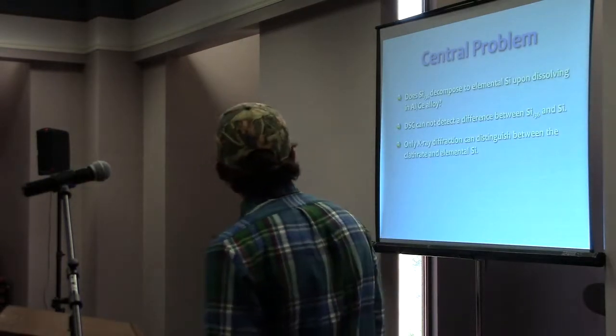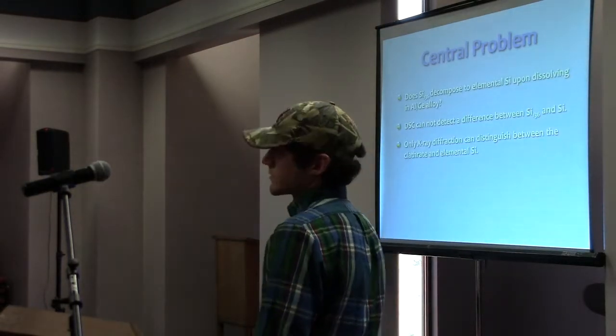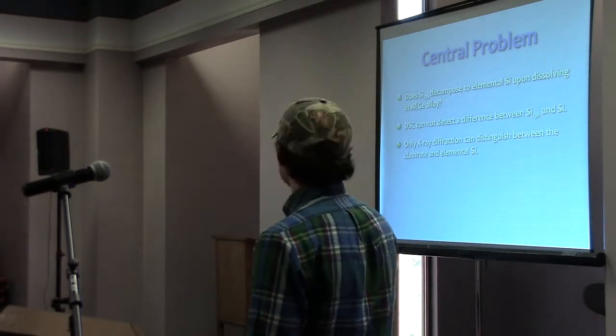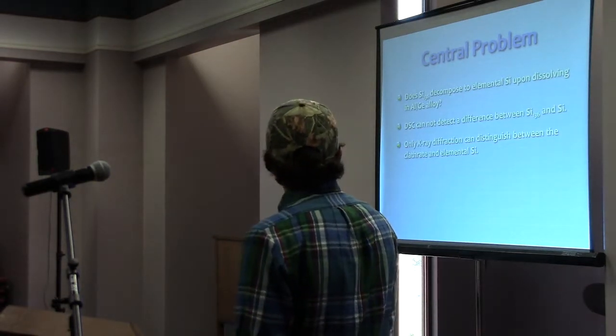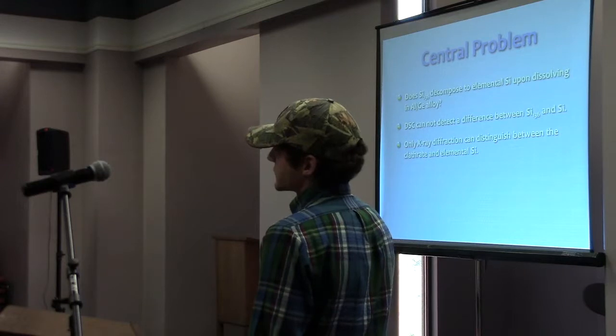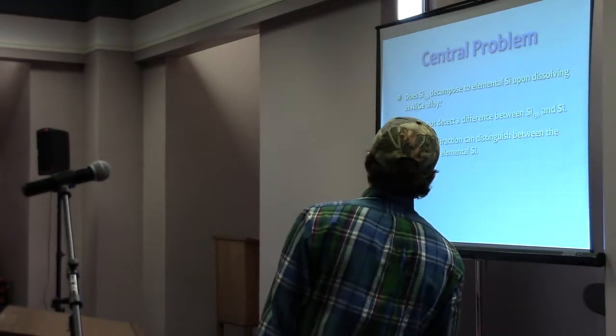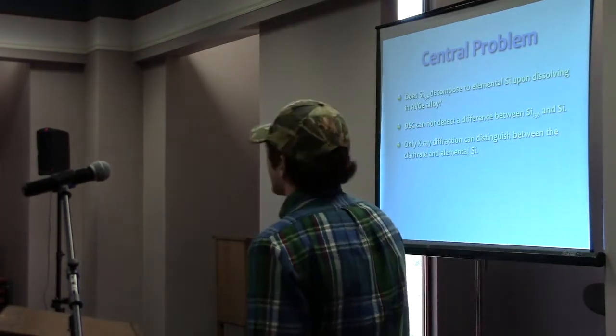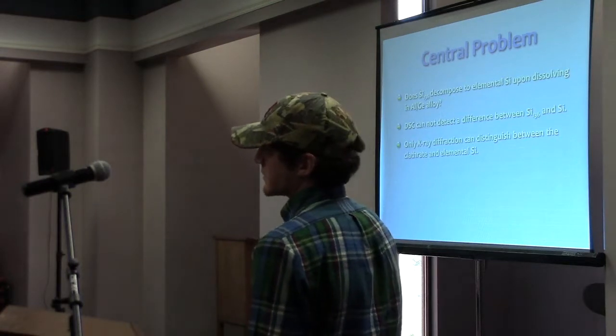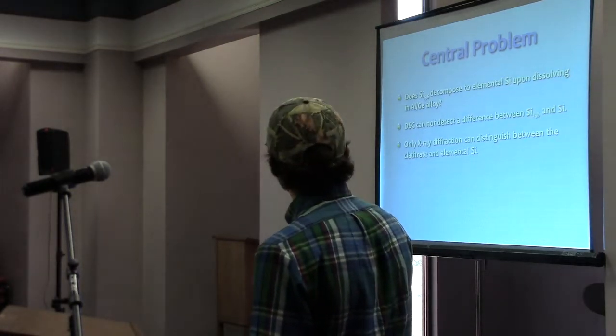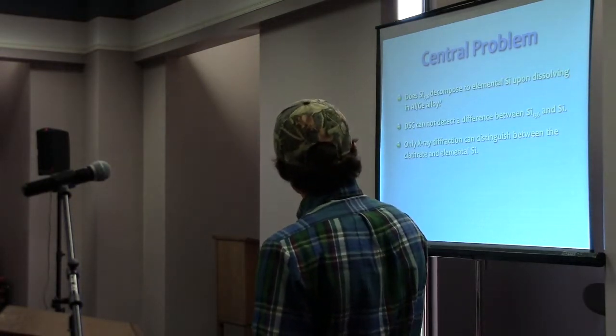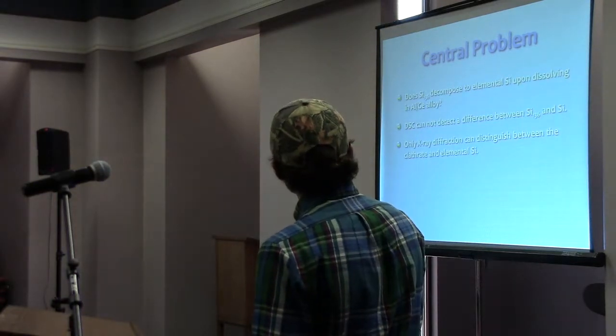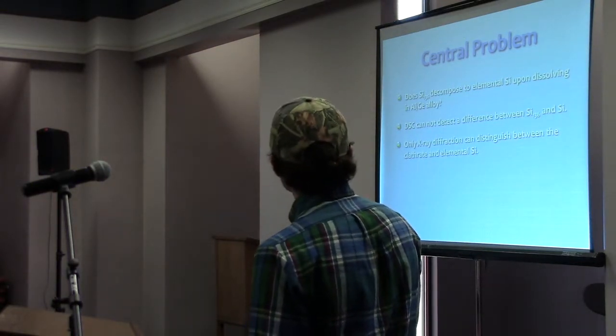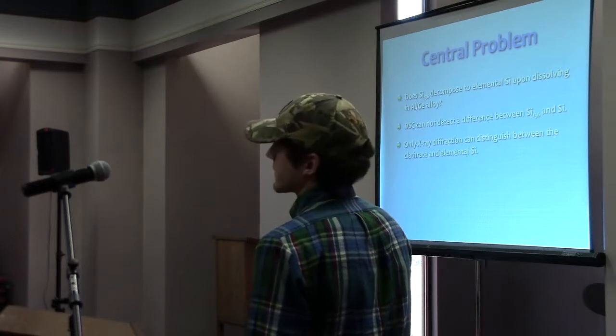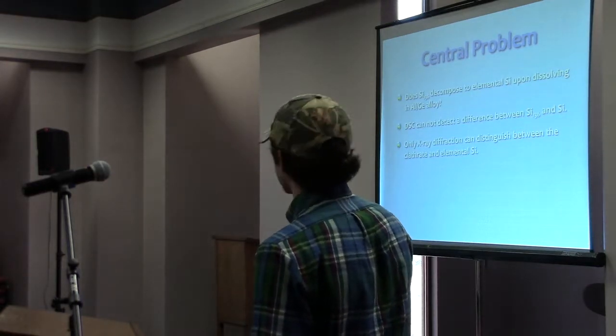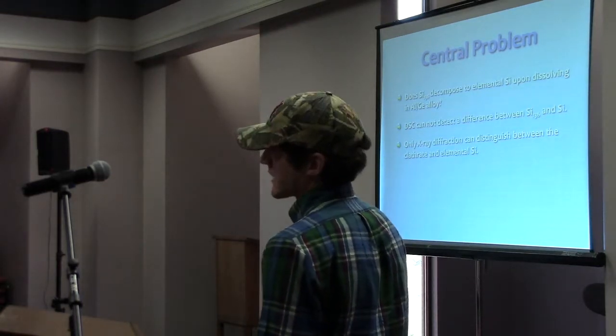Our central problem was that we needed to find out if the silicon clathrate was decomposing when it was melting. And when silicon clathrate decomposes, it decomposes to elemental silicon, and the properties are a lot different for this and it does not carry the thermoelectric properties that we were intending. So in order to see if it was decomposing, we had to use X-ray diffraction because differential scanning calorimetry would not allow us to notice any difference between elemental silicon and silicon clathrate.